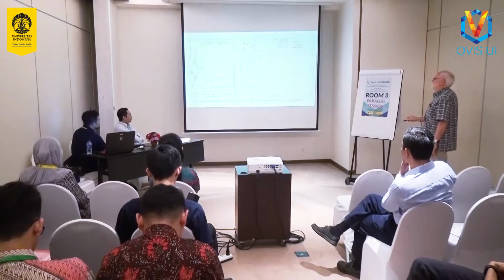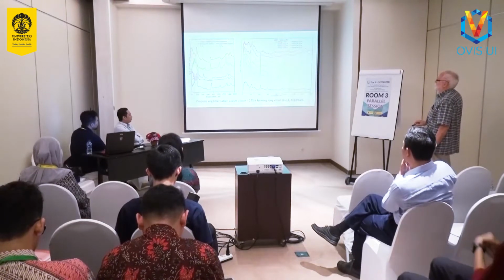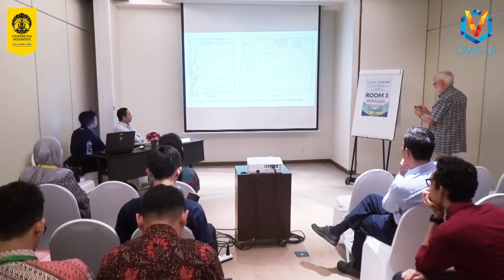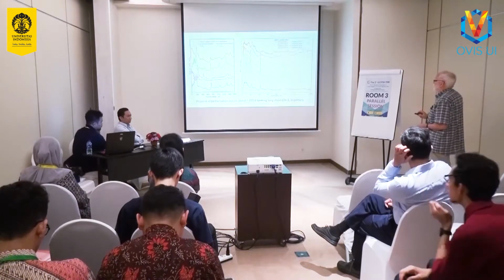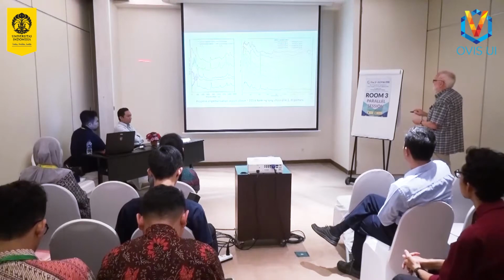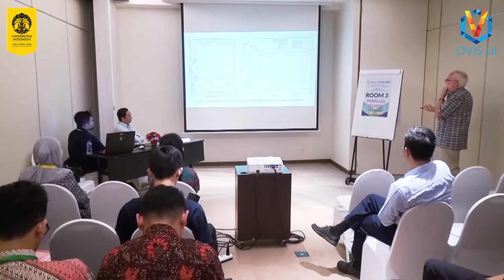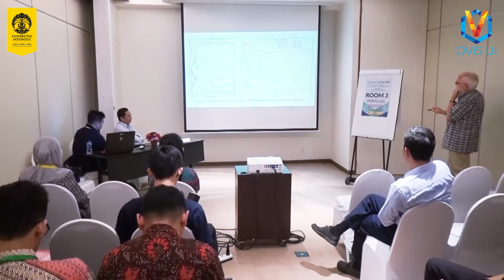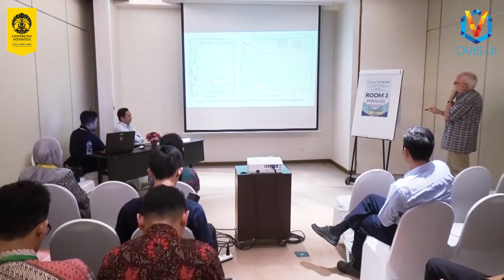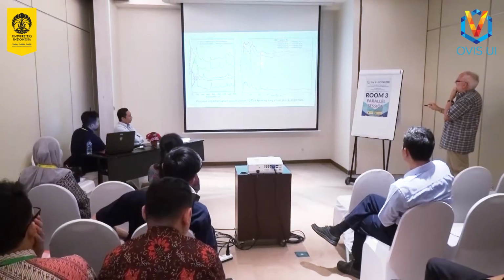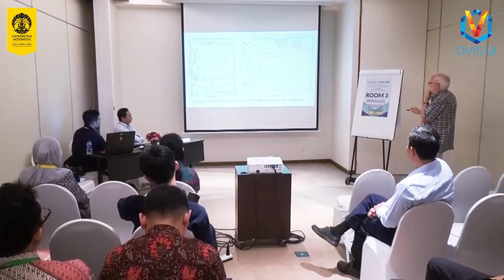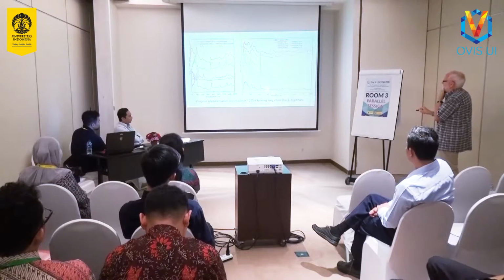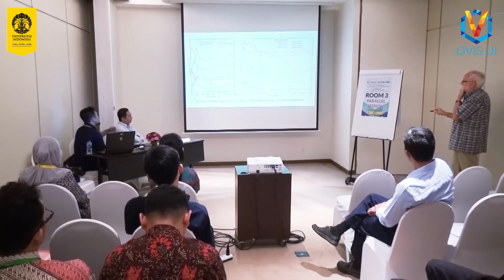Well, we can take that one step further and put in propene at low temperature, and then gradually raise the temperature and see at what point the spectrum changes. Measure the spectrum at each temperature, of course, so it takes a long time, still 5 or 6 hours for each temperature. So that's displayed over here. Maybe keep your eye on this peak here, which is an olefinic CH deformation mode. Propene at low temperature has that mode. As we raise the temperature, that mode disappears. By the time we get to 293 Kelvin, it's gone. The same is true of 1 or 2 other modes there too. This one here, for example, which is also associated with the olefinic part of the molecule.